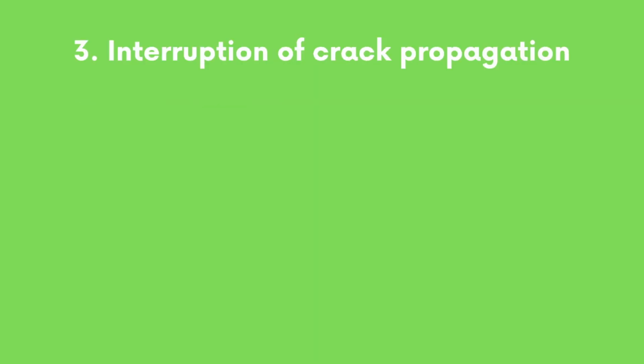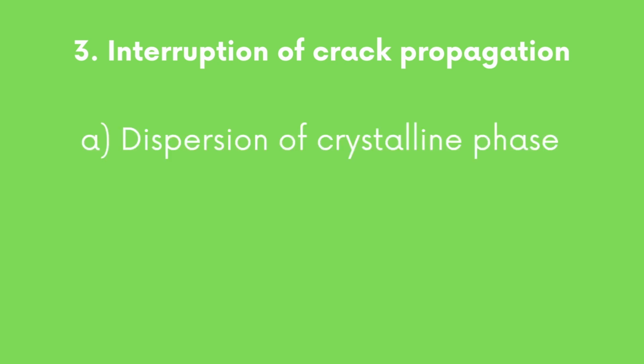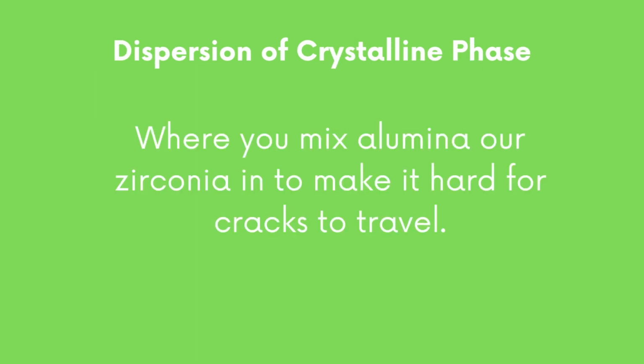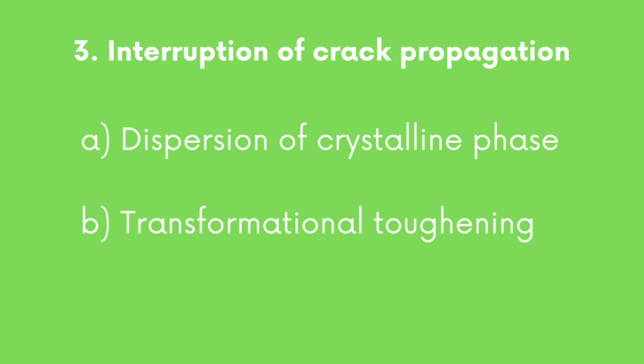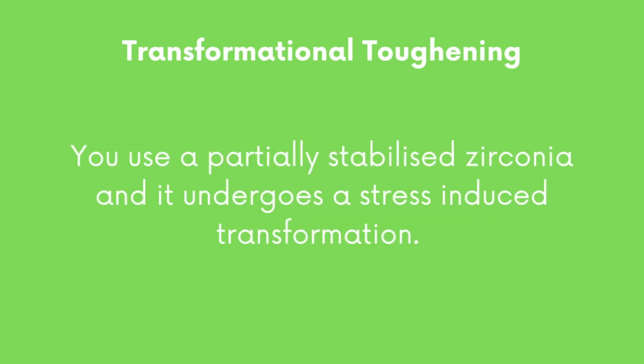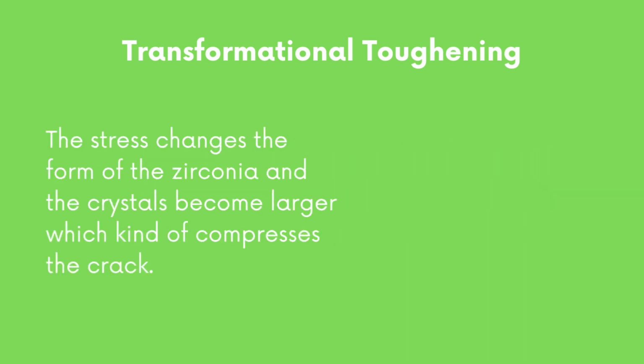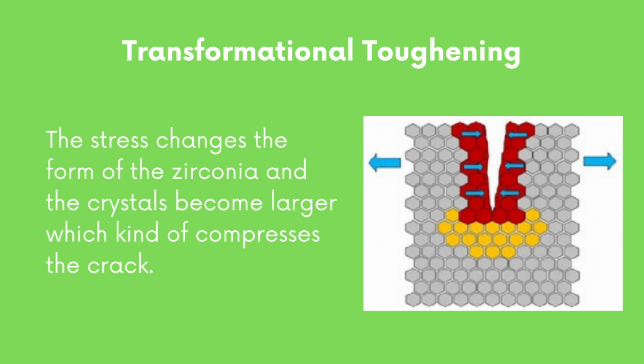Hack number 3, interruption of crack propagation. This is achieved through dispersion of crystalline phase, which is where you mix alumina or zirconia into the ceramic to make it harder for cracks to travel. Or transformational toughening. This is where you use partially stabilized zirconia and it undergoes a stress-induced transformation. The stress changes the form of the zirconia and the crystals become larger, which kind of compresses the cracks. Typically in crowns where aesthetics is required, you're able to use a zirconia or alumina porcelain on the deeper parts for increased strength and layer feldspathic on the outer layers.